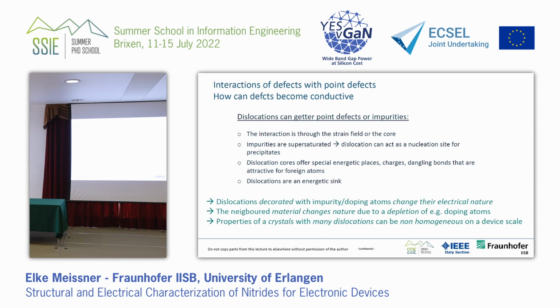Now we learned that dislocations can do something. They can form clusters, they can form bundles, they can go together, they can annihilate. And then you have point defects, which is your dopant, for example, or impurities. If you have a gallium nitride with a carbon-doped buffer, this is the carbon in the gallium nitride lattice, so it should be distributed as evenly as possible.